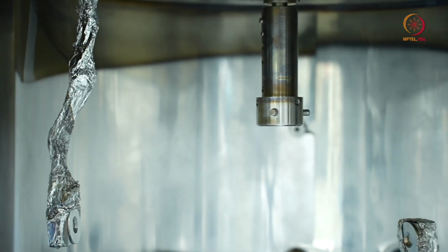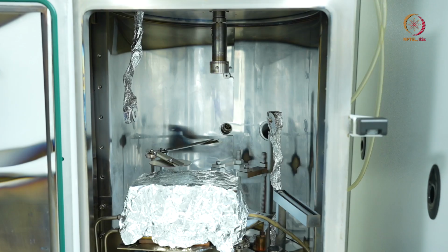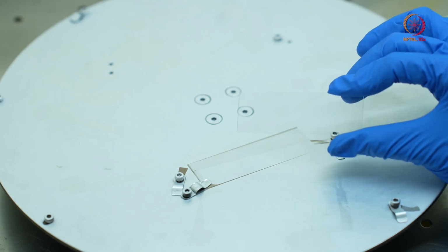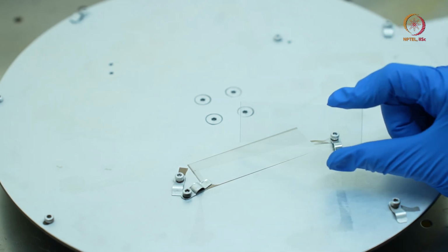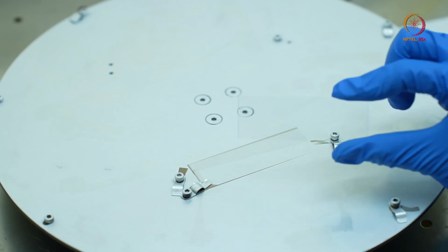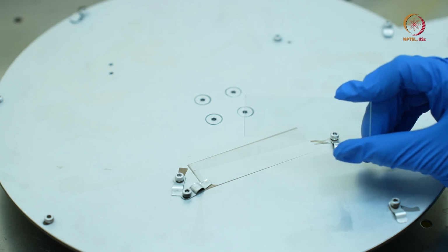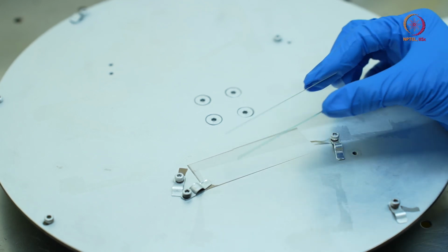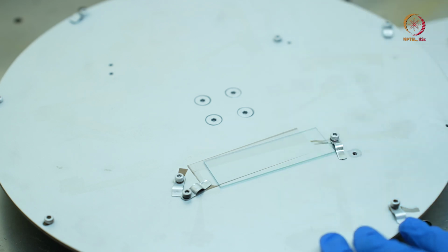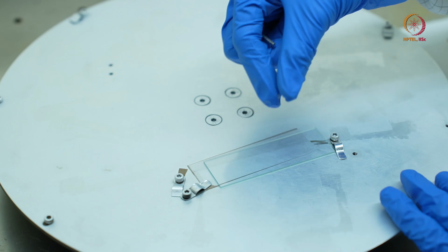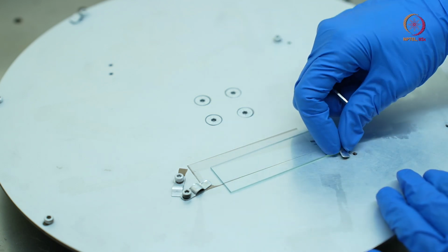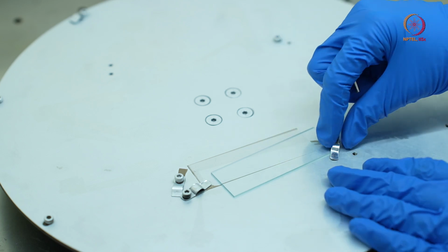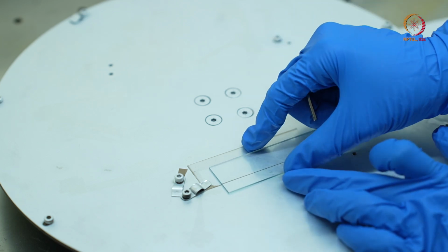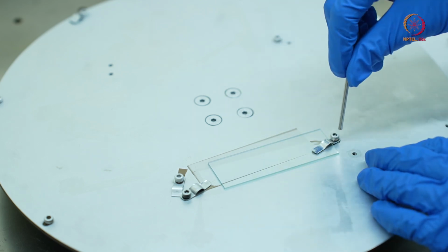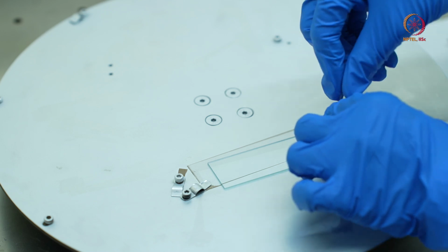Now we'll load our sample. We'll go for sample preparation, and we'll load the substrate holder onto the spindle. This is a glass slide on which we will be depositing aluminium. I have cleaned this glass slide using acetone, IPA and DI water, and gave a nitrogen blow so that the top surface of the glass is very clean for the deposition. I'll place the glass slide onto the substrate holder, and these are the clamps I'll be using to secure the glass slide, so that when we place this substrate holder upside down, the clamps will make sure that the substrate will not fall into the chamber.